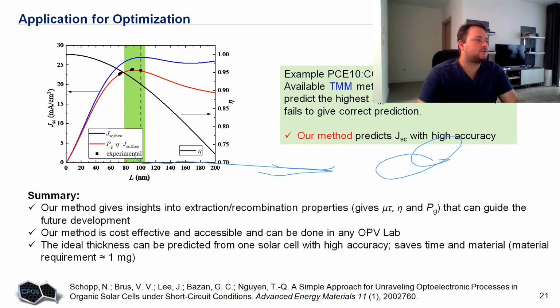Then we can determine all parameters like mu tau product, geometry, recombination prefactor, and simulate this curve in order to understand at which thickness of the active layer will be the maximum short circuit current. And in this particular case, it will be somewhere at 90 nanometers.